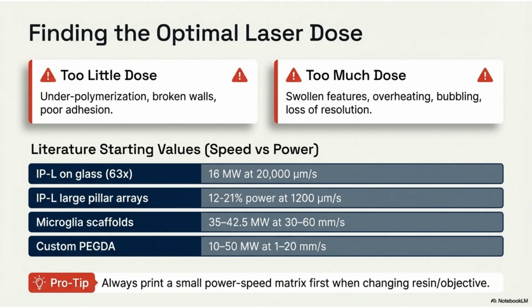Finding the optimal laser dose is critical. Too little dose leads to underpolymerization and broken walls. Too much dose causes swollen features and loss of resolution. Start with a small power speed matrix whenever you change the resin or objective, using literature values as a guide.